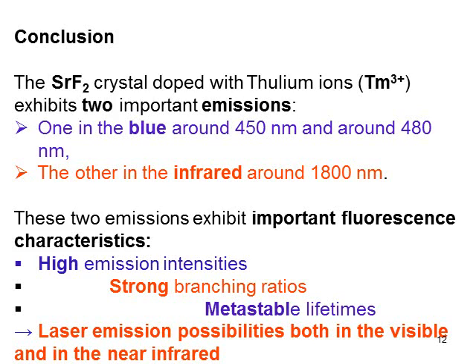In conclusion, the SrF2 crystal doped with thulium ions exhibits two important emissions, one in the blue around 450 nanometer and 480 nanometer, the other in the infrared around 1.8 micrometer. These two emissions exhibit important fluorescence characteristics, that is to say, high emission intensities, strong branching ratios, and metastable lifetimes. The laser emission possibilities are both in the visible and the near infrared range.